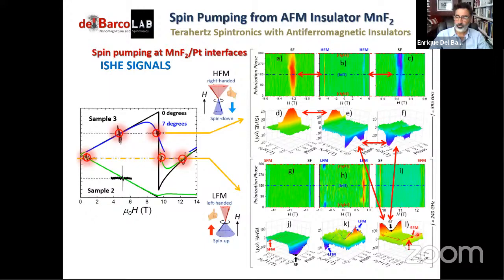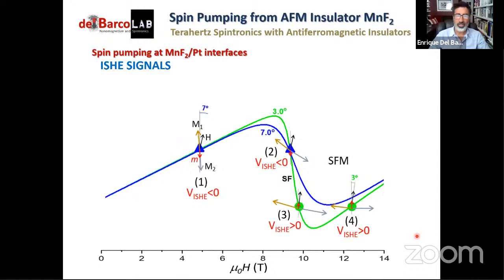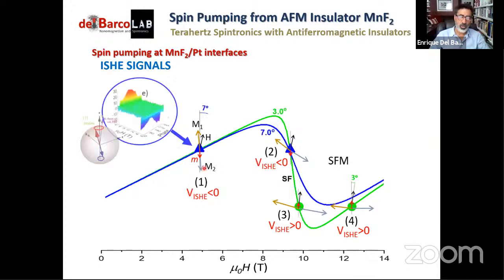All right, so the way we have to understand this in a few words, and with this I will finish, is just following this branch. I cannot follow this branch for a single sample, because, as I say, we have taken measurements on two different samples for these measurements, but it's kind of the same thing. The only difference is that the misalignment is slightly different. And then if we go to low fields below the spin flop transition, Low fields, we're here. Remember, this is the expectation. We have a very circular polarized antiferromagnetic mode. And then this is what we observe, right? So for positive fields, we observe this modulation that is reversed for negative fields, as expected for this mode.